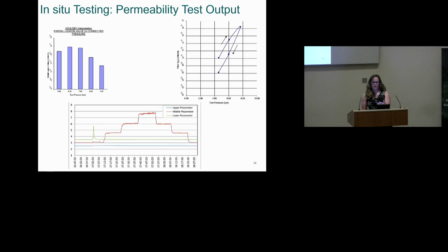So it's quite nice having that confidence in our tests, because I've done packer tests on other sites, and you don't have these electrical transducers, and it's a bit of guesswork as to whether your test zone is really holding the pressure.